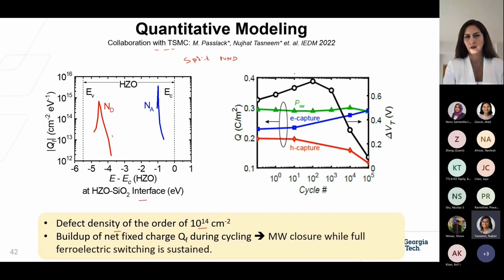And the results from this model also indicated that with cycling, there is a buildup of net fixed charge of predominantly one polarity. And this buildup of net fixed charge is the reason why memory window closes with cycling, even when there is full ferroelectric switching, which is still sustained. So this work was presented in IEDM in 2022.